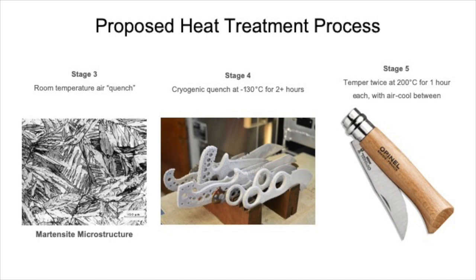The first temper effectively softens the martensite of the quench, but promotes the formation of new martensite within the retained austenite, which requires a second temper to soften. After the double temper, the heat treatment process is now complete, and the blade has a hardness of 59 HRC and maintains a higher degree of strength and ductility.